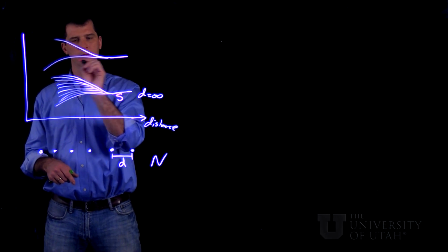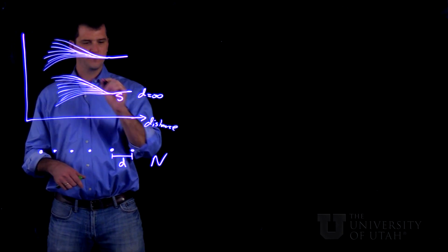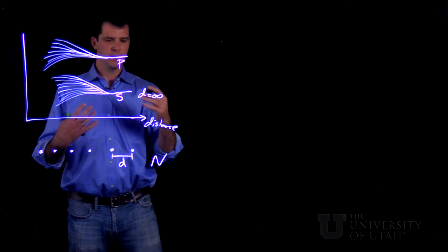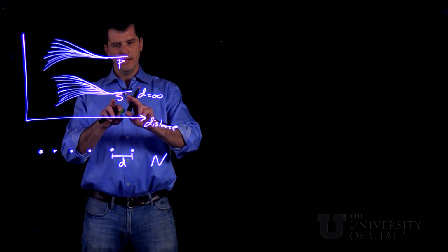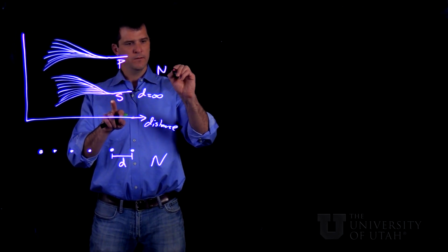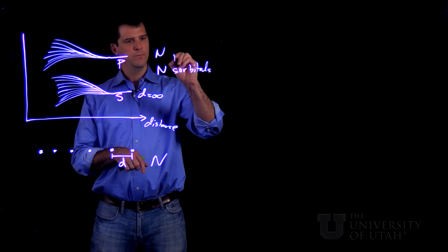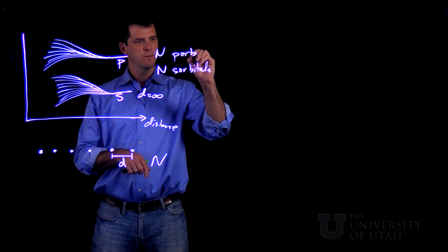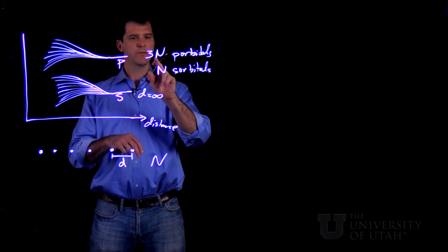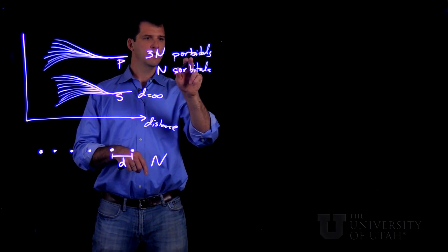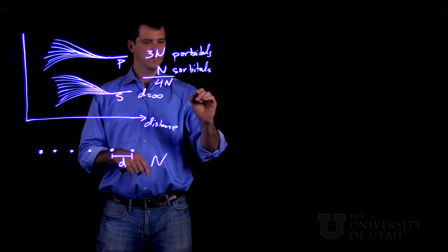We'll have the same sorts of splitting, but the counting becomes a little more complicated. So again, if we have n atoms, we're going to have n s orbitals and n p orbitals for each of the three directions. So we actually end up with 3 times n p orbitals. Each of these orbitals can hold 2 electrons at most.